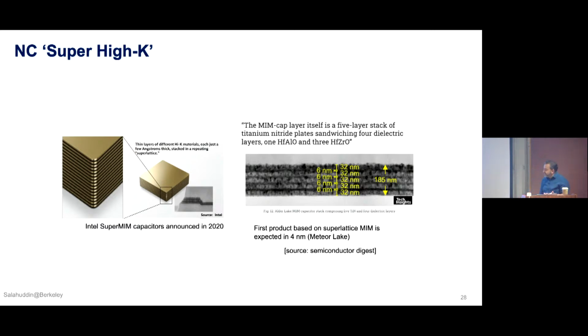You can again see that zirconium oxide has a permittivity of 40, hafnium oxide has a permittivity of 29. If you are trying to increase capacitance, you will never add hafnium oxide to zirconium oxide because you can only get smaller. Except if you are in that negative capacitance regime, where the ferroelectric boost gives you a higher capacitance. And so this is now already used starting from the Intel 10 nanometer node.